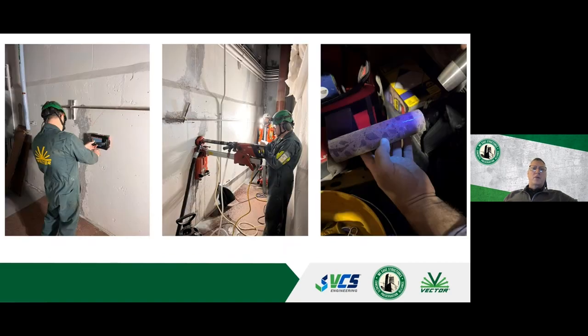And then this is a great photo because he's using a GPR unit to determine where to avoid the steel. He cores into the concrete, pulls out a core, and then under black light in the right-hand photo, you can see that fluorescence from the epoxy injection resin showing up. So he's verifying that the epoxy is reaching and filling that, and you're looking for at least 90% fill.